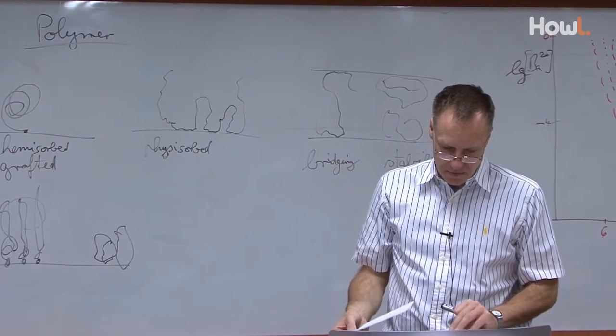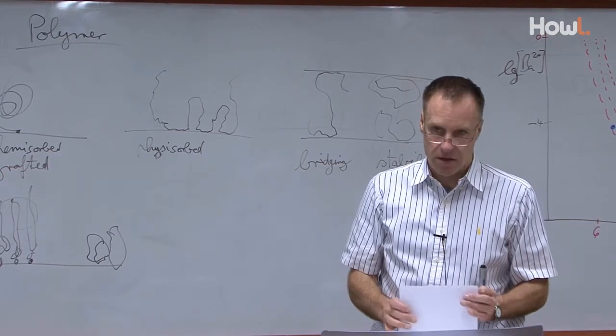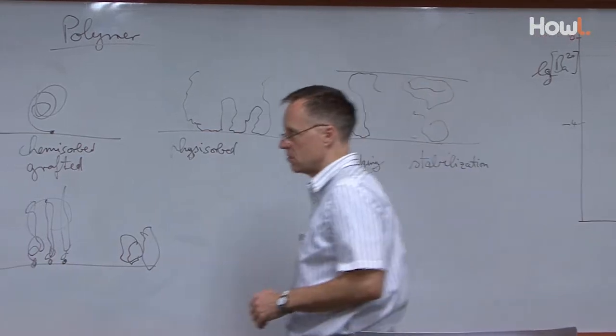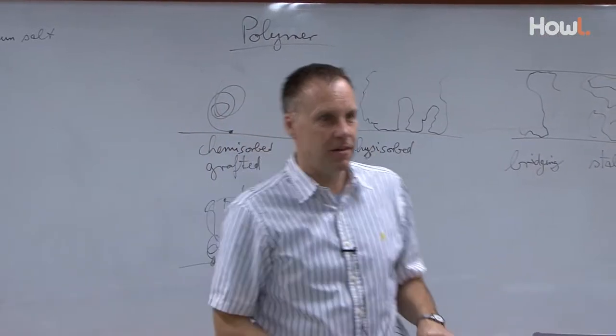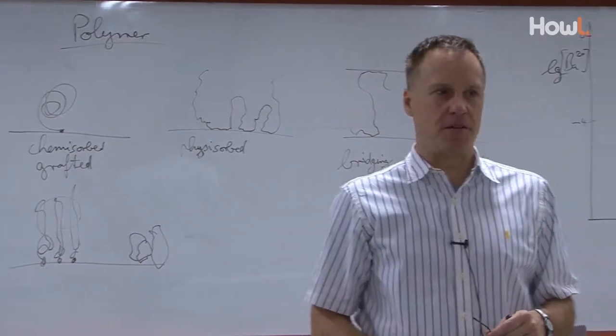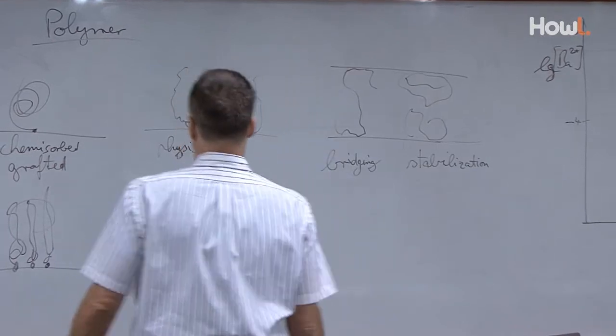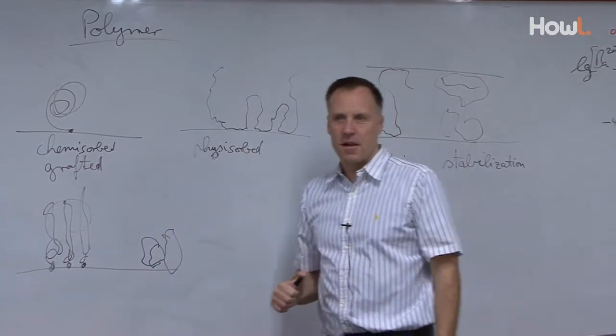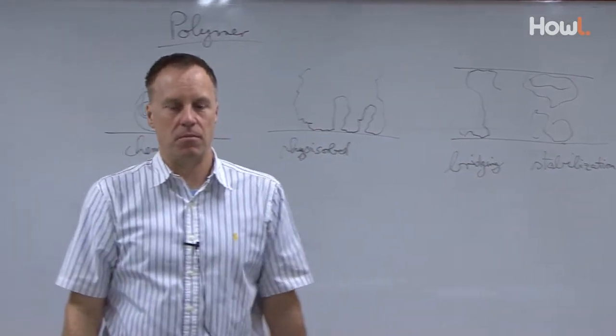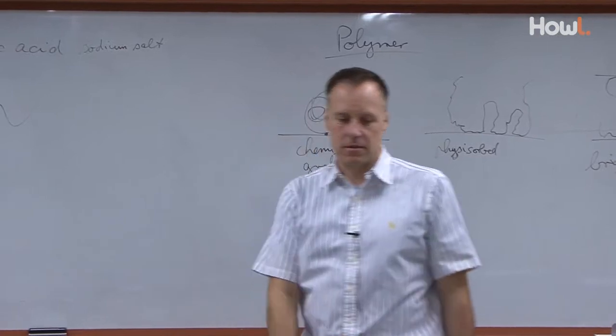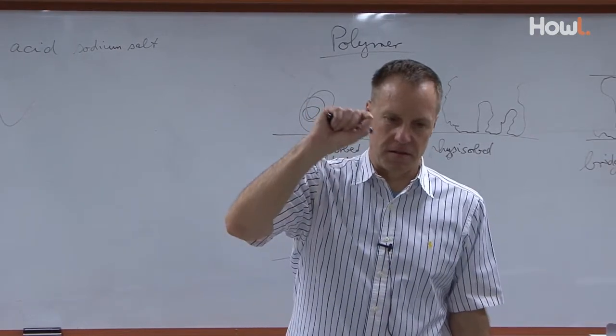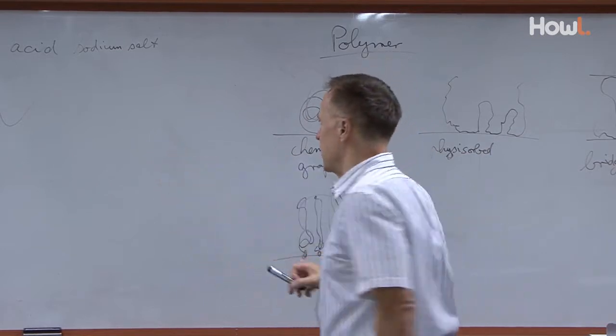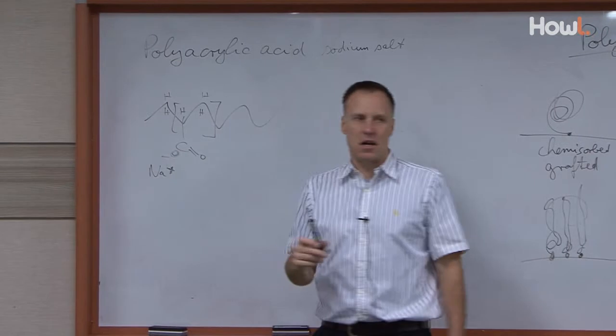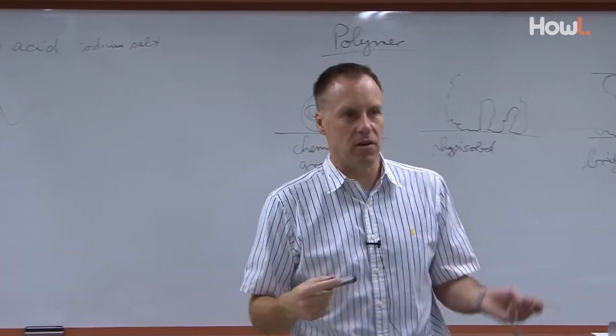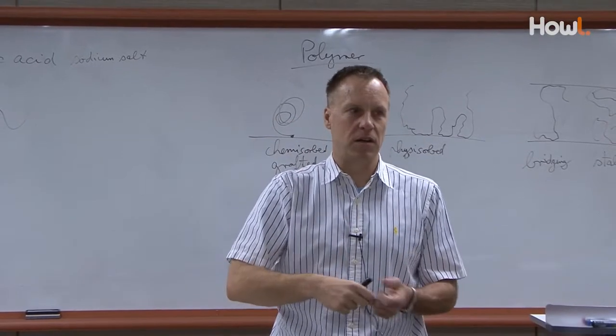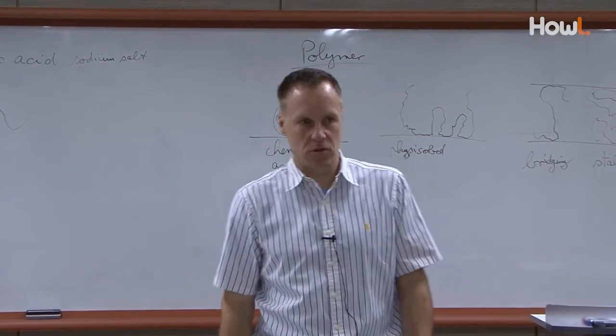And yeah, let's discuss what do you think for barium titanate. Would this be a good polymer to use? Would it work when you use such a polymer to adsorb on the surface? So it's a homopolymer. It would physisorb in some way like this on the surface. Let's say the one part is, I wiped out the chart. Barium titanate is typically quite negative over a range. So these are negative ions on the polyion system here. So that is not the best part. But it still will anchor on the surface. And as soon as you get barium ions leaching out, it will bind to the barium ion, which binds to the surface. So from that part, it will work.